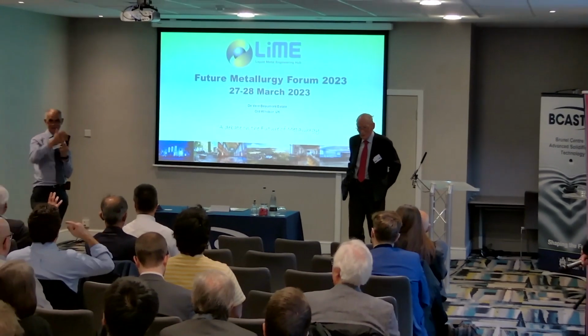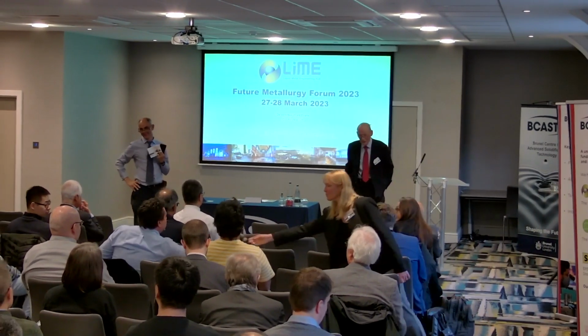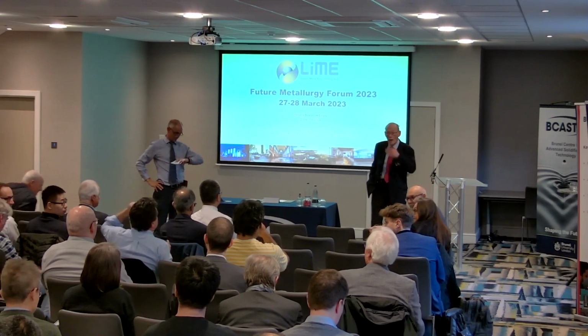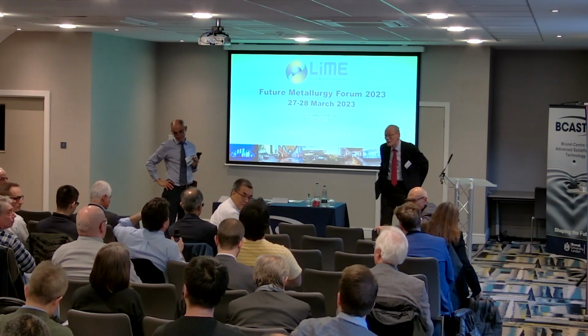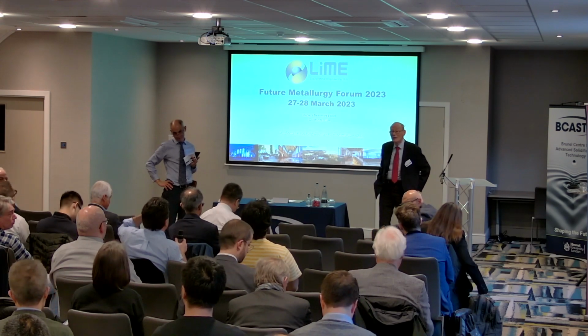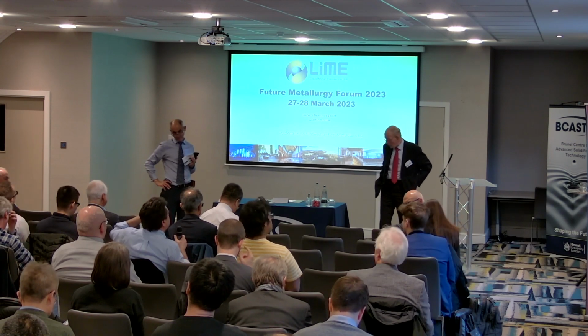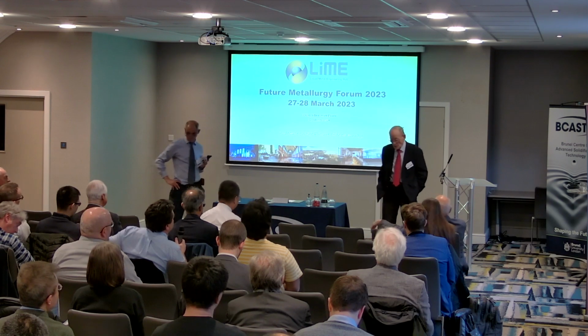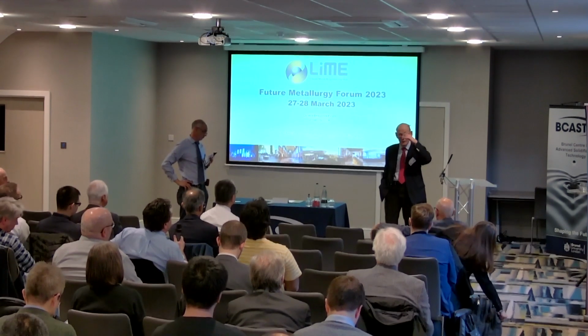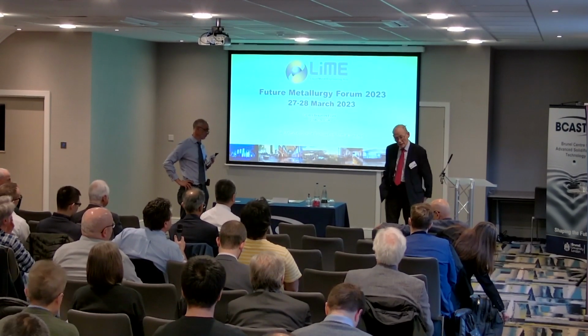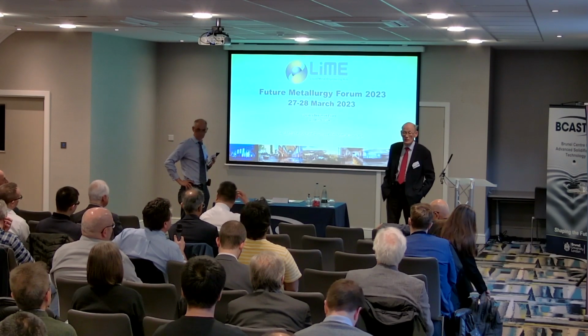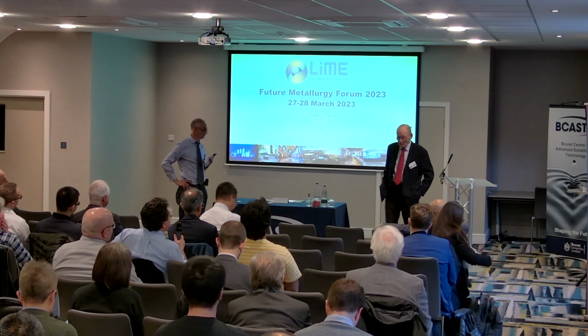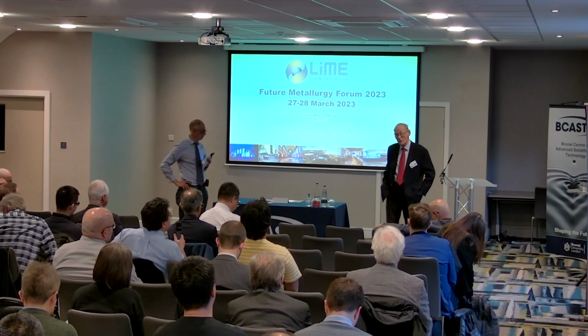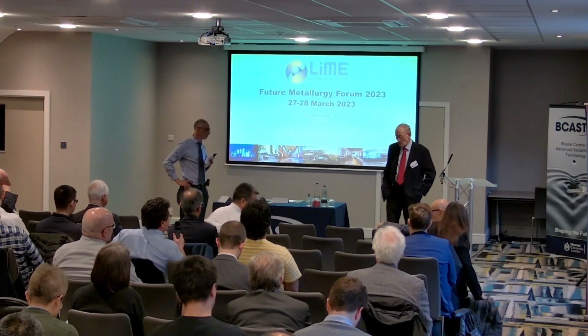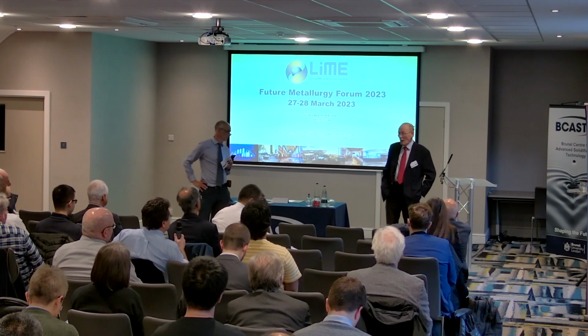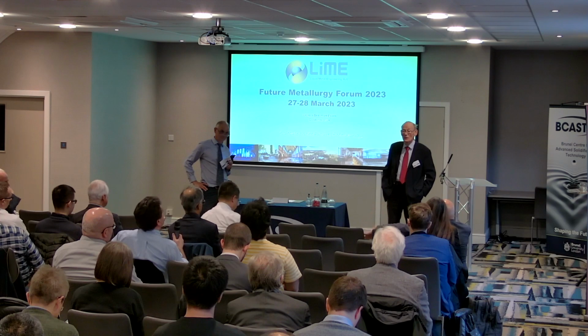Questions? So thank you very much. Very interesting work. Can I ask, you mentioned in the beginning that the molybdenum silicon boron alloy has low oxidation resistance, and at the end you said... Oh, no, it has oxidation resistance, but the recession rate, that is the diffusion of oxygen through the scale, the borosilica, reacts with the underlying alloy to a too great an extent. We've addressed that by changing the boron to silicon ratio in the coating and adding a little bit of aluminum oxide. So we've annealed samples in air at 1700 degrees Celsius for days, and the weight change is 1 milligram per square centimeter, which is negligible.